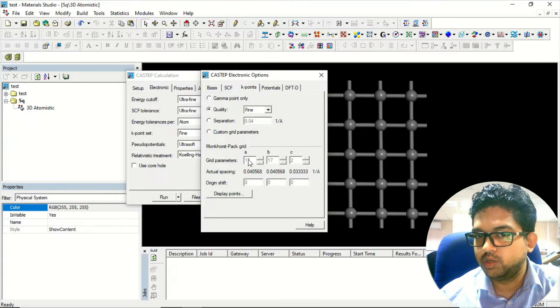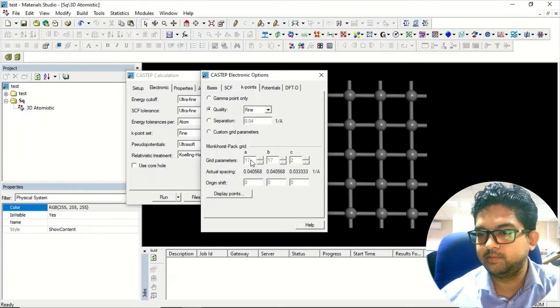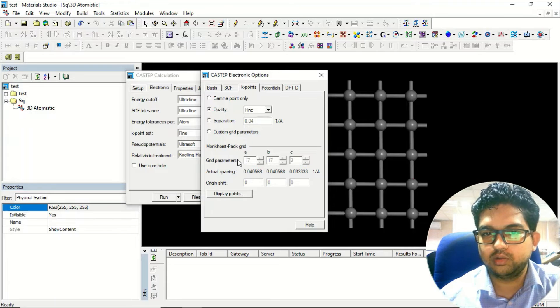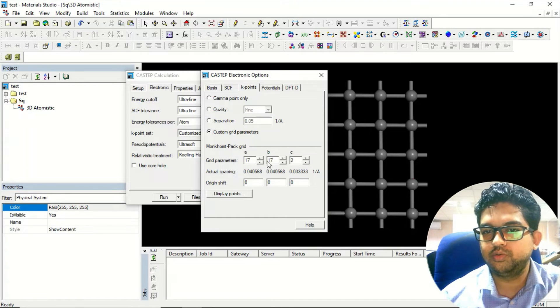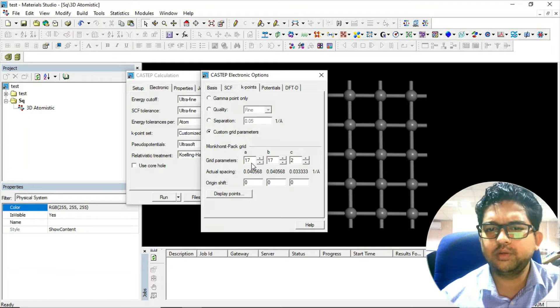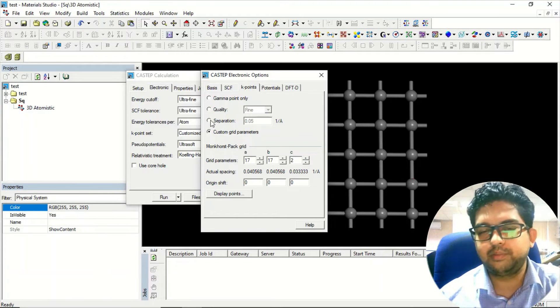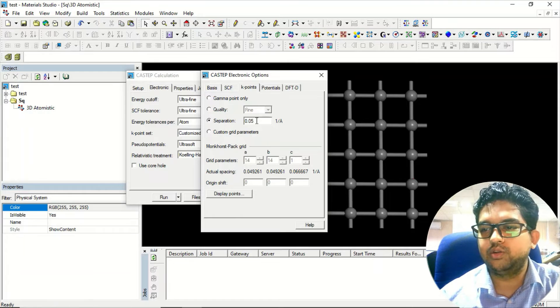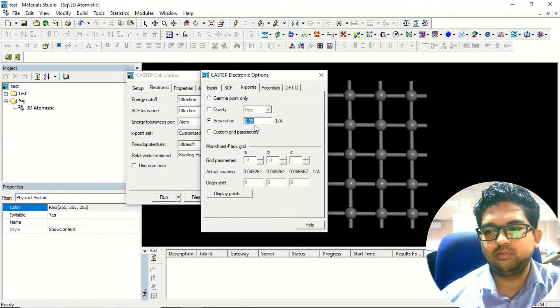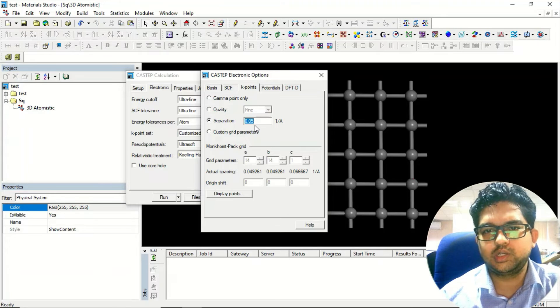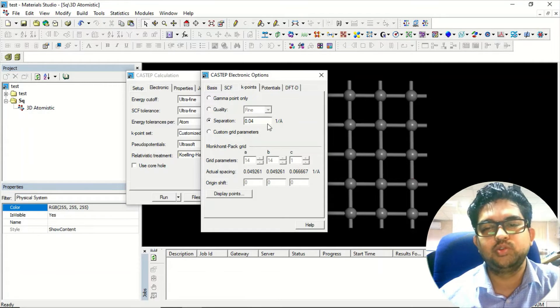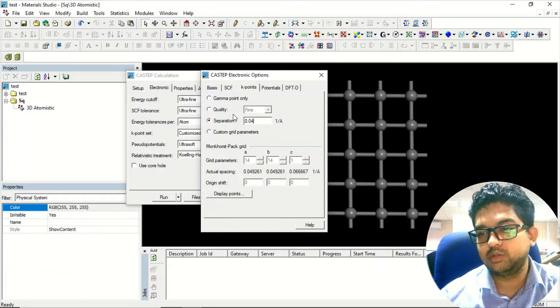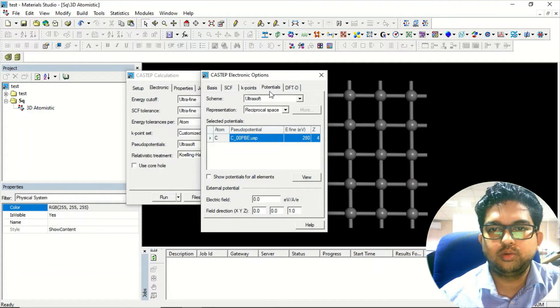These are the k-points. There are two ways to give k-points: based on separation, or based on a k-points grid like 10×10 or 5×5. If you want to give the MP grid, click on custom grid parameters and select — for example 20×20 — whatever you want. Personally I prefer giving the separation between k-points. A value of 0.01 gives the best accuracy; 0.04 is also okay for publishable results, but for more accurate results you need to decrease the value, though it increases computation time.